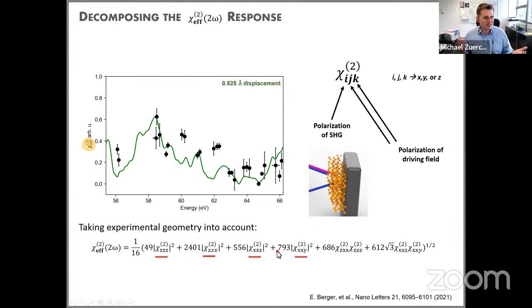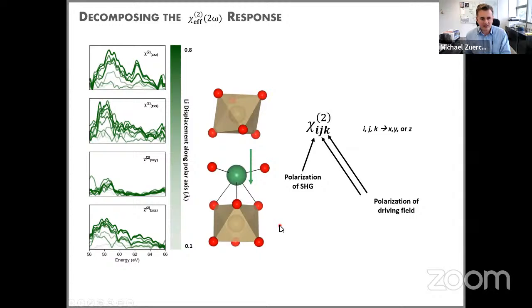That's all they can do. They basically run a TDDFT and calculate the second order response. They calculate the different tensor components, and then this green curve comes from plugging these tensor components for each frequency into this analytic formula to calculate the projected response. So some of the error can stem from misalignment of our crystal, for example, so that we measured a slightly different plane, a slightly different projection. This is what makes these experiments and the planning of these experiments quite complicated.